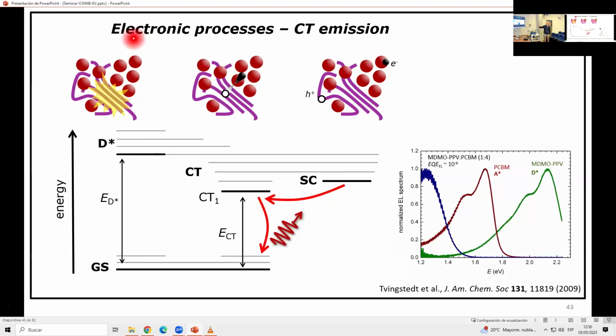And it indeed happens, and that's why I emphasize so much that you can use a solar cell also as an LED, because it's also the same device architecture. So if you use your solar cell, your blend material, your donor acceptor blend like this, as a light emitting diode, the emission spectrum, this is an old material, PPV, blended with acceptor, is very redshifted as compared to pure material. So you don't see any pure material emission anymore. If you use your solar cell, your donor acceptor blend as LED, it's also a very bad LED.